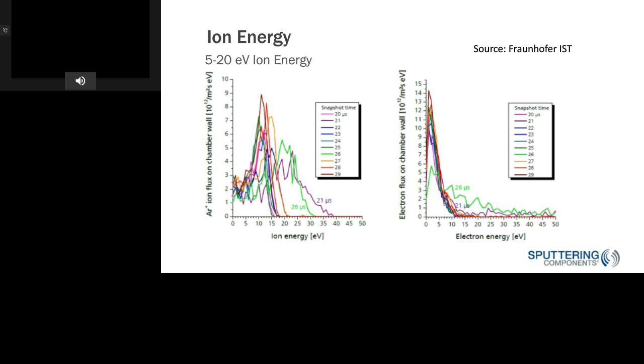So usually the lowest ion gun energy is maybe around 75 to 100 electron volts, but more commonly higher than this, maybe 150 to 250 electron volts. And this can be pretty damaging to the substrate, whereas we're running at 5 to 20 electron volts and still able to treat the substrate